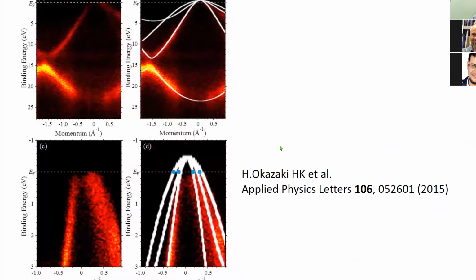And a very recent result, we also obtained in ARPES spectroscopy in the same group, with young people collaborating with Dr. Yokoya's group. I think we get a relatively sharp plateau in angle-resolved photoelectron spectroscopy, and the Fermi level really cuts into the valence band. Well, that's what we saw from this spectra.